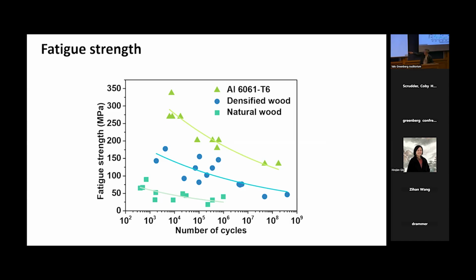darker green line over there at the bottom is the natural wood. Okay, it does fatigue, and it typically fails by fatigue at less than 1 million cycles, and the fatigue strength ranges from a few tens to less than 100, more likely around 70 megapascals. And you also notice the decreasing trend: if you reduce the cyclic load, you can elongate the life of the sample.